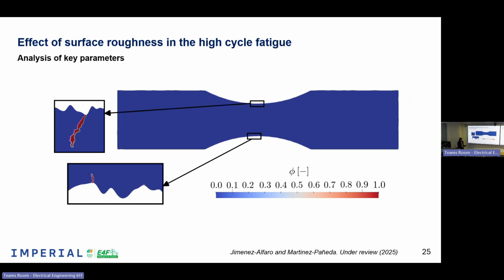After that, we have included here just the damage profile, just to show you how it works. So these peaks are acting as stress concentrators, and in those peaks we have very big stress so that the crack is nucleated. Once the crack is nucleated, that is represented in red color, then it is propagated until it arrives at the center of the specimen, more or less. Since we are in a force control problem, at a certain moment, the damage variable will cover a huge region, because in a force problem, it's like the force goes, stops at a certain value, and the displacement can be infinite in the results of the force displacement curve. So here it is translated in a huge region where damage is equal to 1. At this point, we define our fatigue failure, and we say that we have arrived at the number of cycles we are interested in.